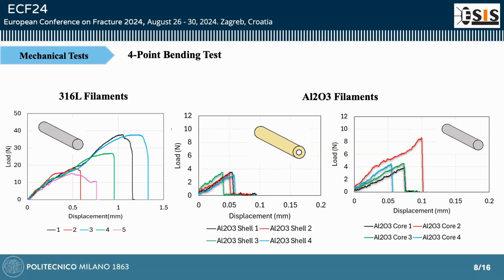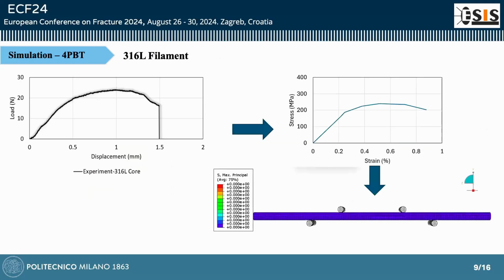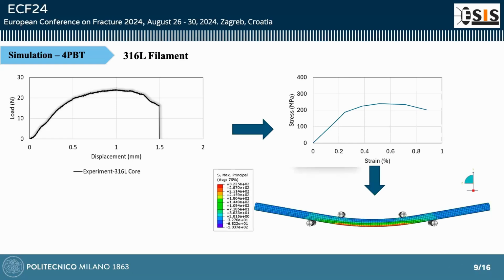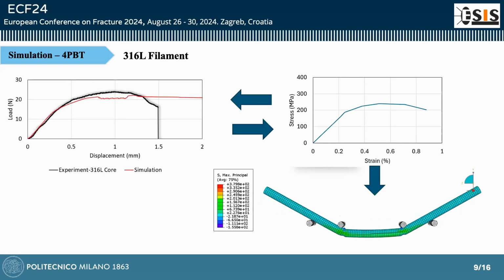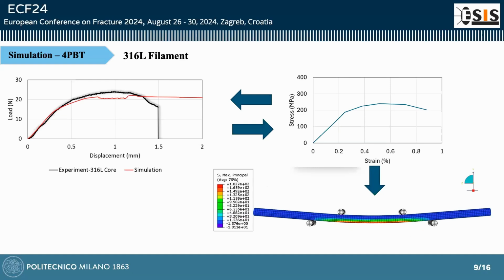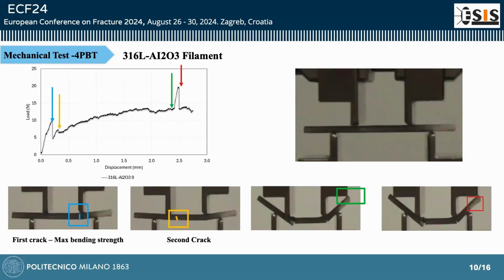In this slide, we are presenting the typical output of the 4-point bending test experiments. As we see on the left, the pure metal results are presented. And we see that they have a ductile behavior, and the tensile strength values are dispersed. On the right, we see the results of the 4-point bending test of ceramic filaments, which are made of alumina, and we see that they are brittle. By using the results of the bending tests that we had, we extracted the material characteristics of metal, and we used it as the input of our simulation by Abaqus software. And these data are going to be used to model and simulate the composite scaffolds in advance.